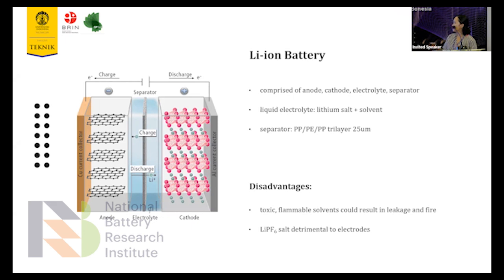The disadvantage of the commercial battery is that it contains liquid electrolyte, which is prone to leakage, which could result in fire. And also the salt that is being used, lithium hexafluorophosphate or LiPF6, is very detrimental to electrodes, so it can be harmful for the lifetime of battery.